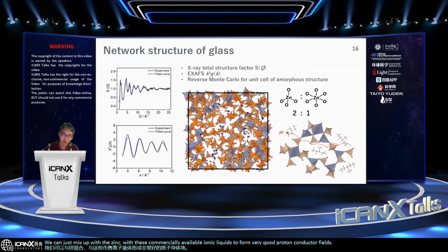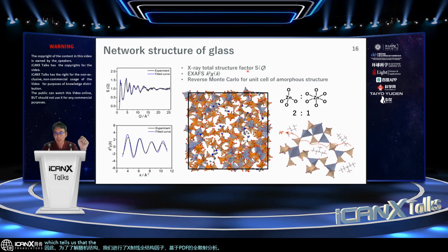But we also need to understand the structure of the glass, which is very difficult. To understand the randomized structure, we conducted X-ray total scattering based PDF analysis, which tells us about the middle-range periodicity in the structure, and X-ray absorption to understand the coordination geometry around the zinc, with the use of reverse Monte Carlo simulation to illustrate this glass structure.